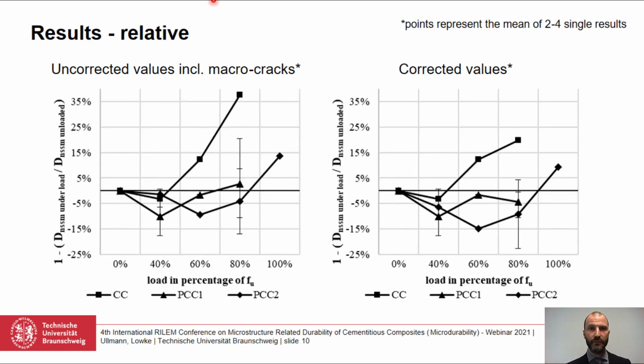And what I just showed you becomes even more obvious if we depict the results relatively, so referring to the non-steady state chloride migration coefficient that was determined at 0% loading. Again, we have the uncorrected values, including the macro cracks on the left, and we have the corrected values on the right. We see again that the CC mortar is much more affected by the external load than the PCC mortars. And what I did not point out so far, and what actually was the intention of the investigation we made, the Young's modulus has an effect on the impact of the external load. And that is what we see when we compare the 2 PCC mortars again. The PCC1 mortar, that is indicated by the triangles, lies slightly above the PCC2 mortar that has a lower Young's modulus than the PCC1 mortar.